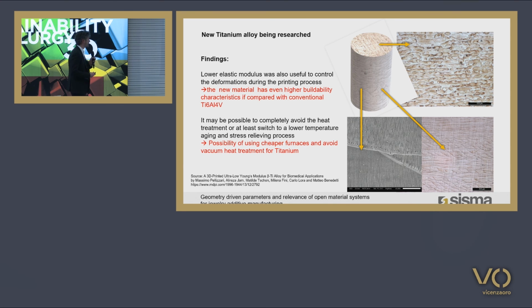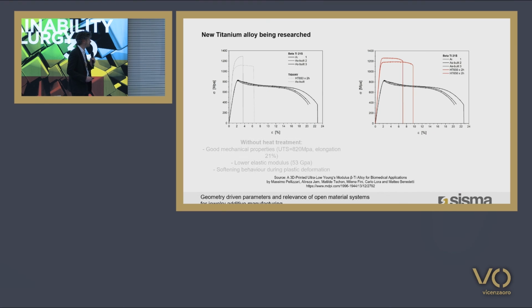So for the new material developed by the University of Trento, you can find the source for their document here, and we did all the manufacturing of the samples. We found that this new material has even higher buildability than conventional titanium 6.4, so it needs even less supports, and it's also a material that can be heat treated without using argon and at lower temperatures. So this is a comparison of titanium 6.4 grade 23 and this new alloy.